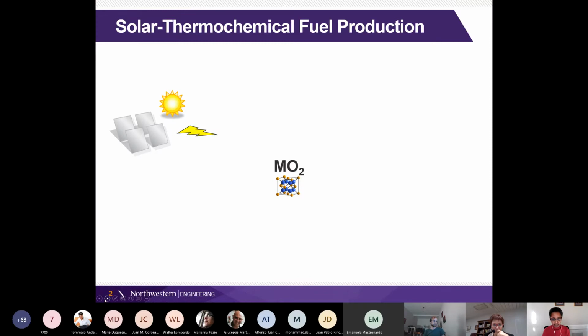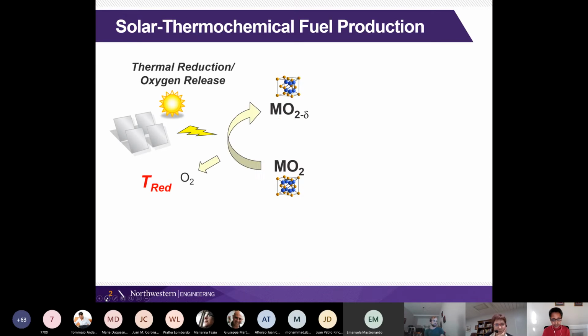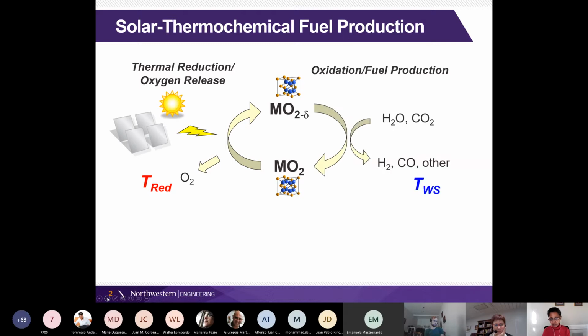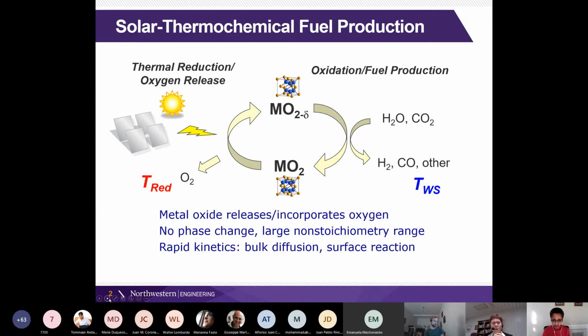So the idea is very similar in the sense that we have a metal oxide. We're going to take it to high temperature, allow it to get reduced, and then in this case, expose it to steam or carbon dioxide with the aim of extracting the hydrogen or the carbon monoxide for future use. What we are using here, in contrast to the phase change materials that were just described, are materials that release oxygen and incorporate oxygen without a change in crystal structure. And that is beneficial because that means that we have very high bulk diffusion through this material, and typically also that's associated with fast surface reaction rates.